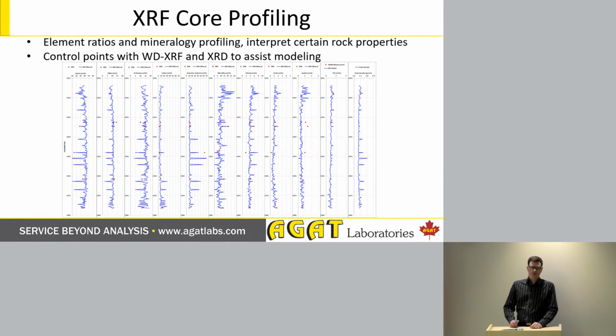XRF Core Profiling is something that we are seeing more and more lately as a type of chemostratigraphy analysis. What we're doing is we're taking a handheld XRF gun. It's very interesting. It looks like a futuristic ray gun. We're putting that onto the core surface, and at 5 or 10 centimeter intervals, we're analyzing a point to obtain the elements that are present at that point. The type of gun that we use can carry out all elements from sodium and up. It is unable to get carbon at this time, but we can actually model some of the other elements based on what we're seeing if we have good data from other sources.